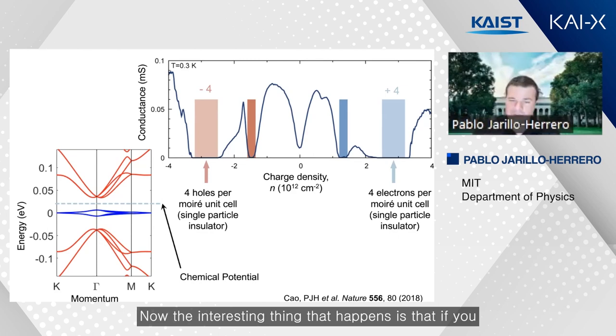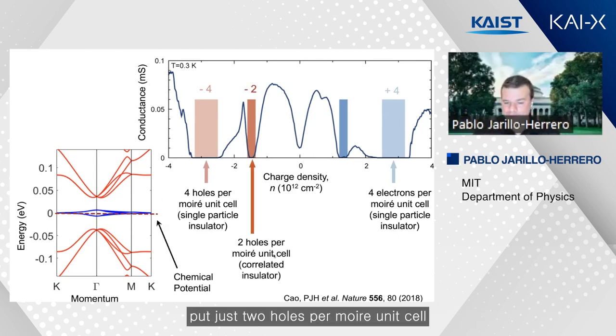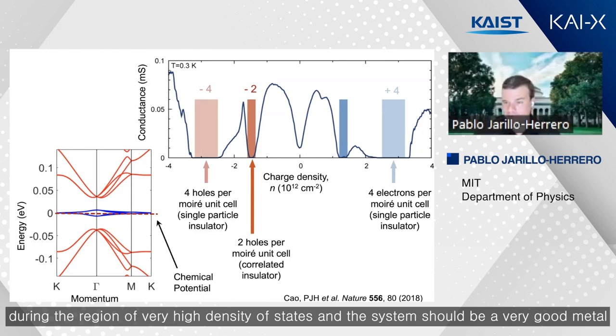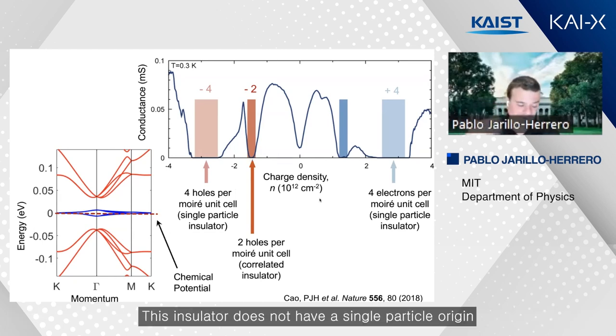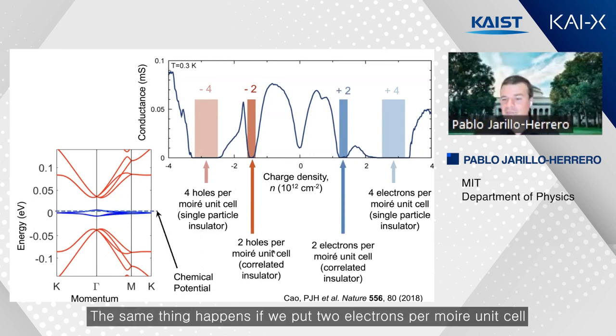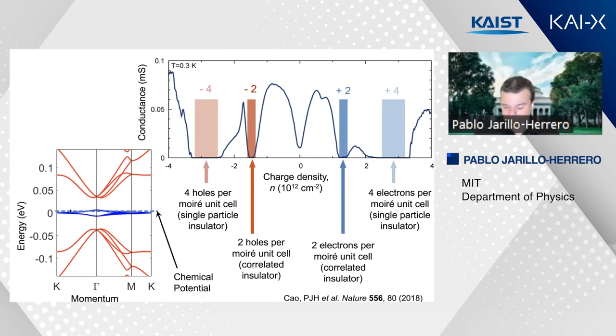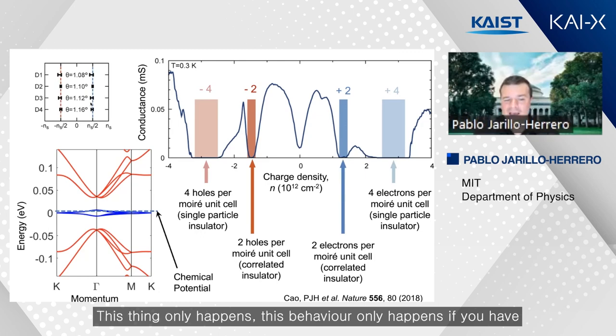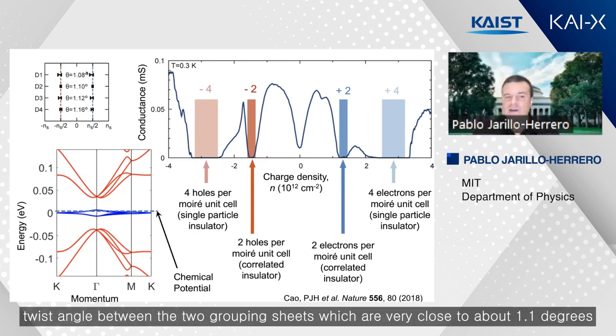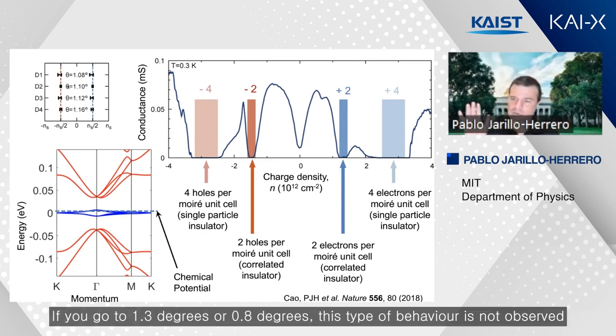Now, the interesting thing that happens is that if you put just two holes per moiré unit cell, your chemical potential is in the middle of the valence band here. In principle, magic angle graphene with the chemical potential there should be a very good metal. You're in a region of very high density of states, and the system should be a very good metal. However, as you can see, the conductance of the system is zero. The system is an insulator. This insulator does not have a single particle origin, but it's a correlated insulator. The same thing happens if we put two electrons per moiré unit cell. You put your chemical potential here, and you have a correlated insulator. This behavior only happens if you have twist angles between the two graphene sheets which are very close to about 1.1 degrees. If you go to 1.3 degrees or 0.8 degrees, this type of behavior is not observed.